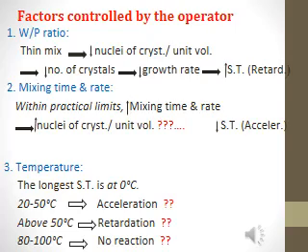But above 50 degrees centigrade, the reaction is retarded, because increasing the temperature of water above 50 degrees centigrade will lead to increasing the solubility of the dihydrate to approximate the rate of dissolution of the hemihydrate. But the hemihydrate dissolution is still more. Okay, so retardation of the reaction will take place.